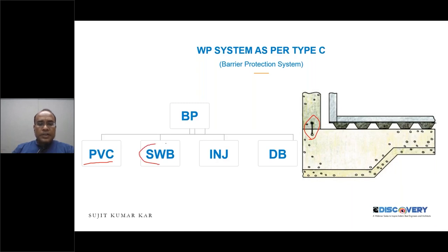Then the swellable type waterproofing. See, there are certain drawbacks of these PVC water stoppers. Because of that reason, we can use some swellable type. The swellable type waterproofing system is basically of 10 mm by 10 mm or 20 mm by 20 mm dimension. When we place this kind of system in the construction joint, and it comes into contact with water, it swells and minimizes the gap, so that water will be blocked over there, so it will provide a complete barrier system.